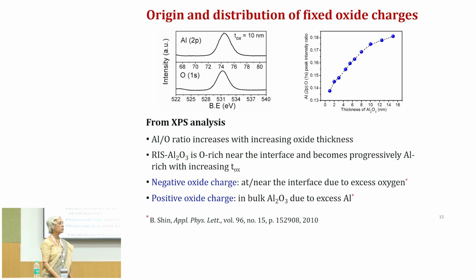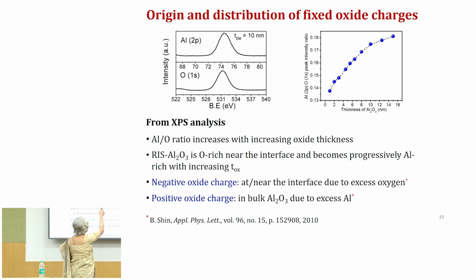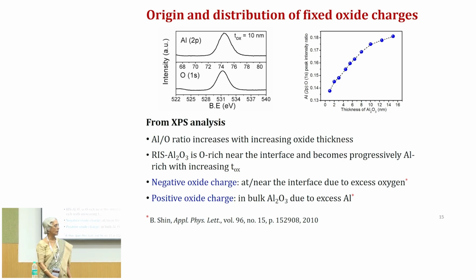So, as I said, we have done a compositional analysis also, and we looked at the distribution of the fixed oxide charge. As you can see here, when we plot the aluminum to oxygen ratio versus the thickness of the aluminum oxide, what we find is that at the interface it is more oxygen rich, but then as we are moving away from the interface it is becoming progressively aluminum rich with increasing TOX. So, we have negative oxide charge at or near the interface because of excess oxygen, whereas in the bulk of the aluminum oxide we have positive oxide charge, and that is what is giving rise to this non-monotonic nature of the threshold voltage variation.